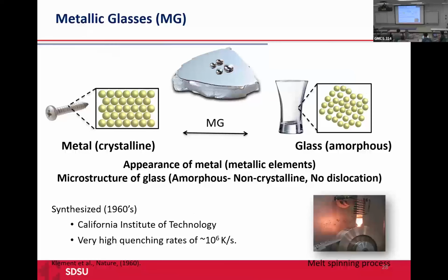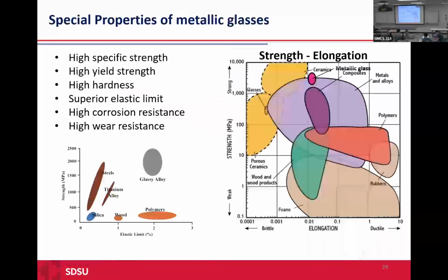fast quenching of the molten alloy, for example, at the rate of 10⁶ Kelvin per second. At that high speed, usually atoms don't have enough time to arrange themselves in the crystalline structure. Then the final structure would be amorphous. Because of this amorphous structure, usually they have some special properties.